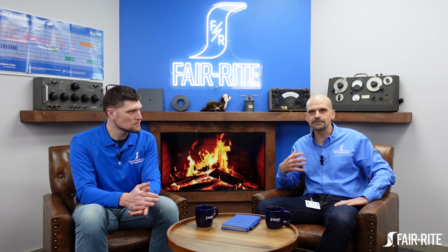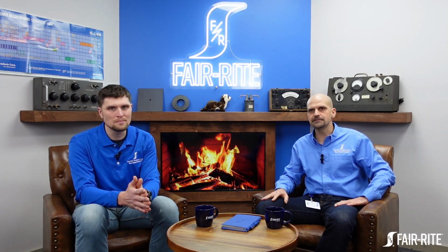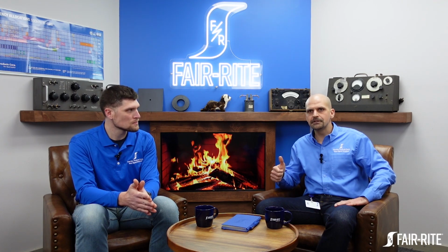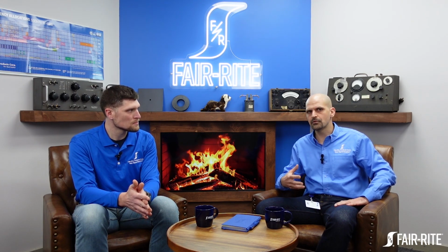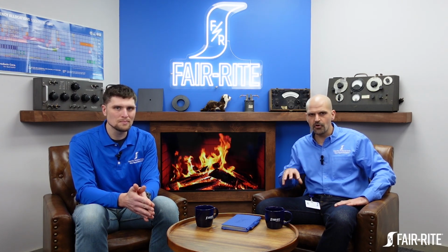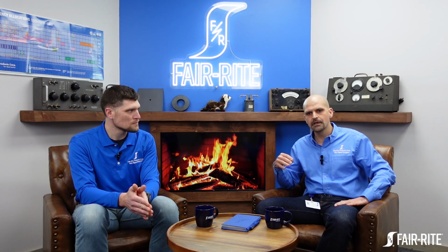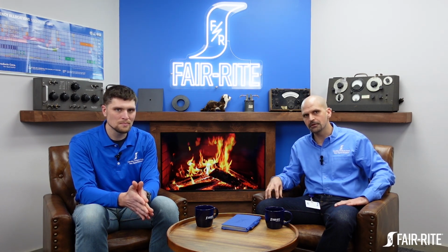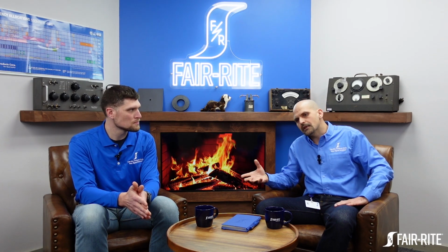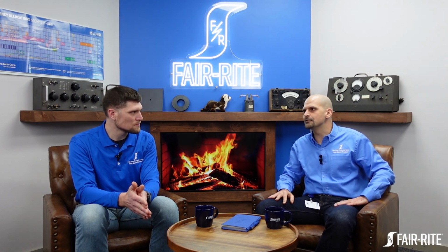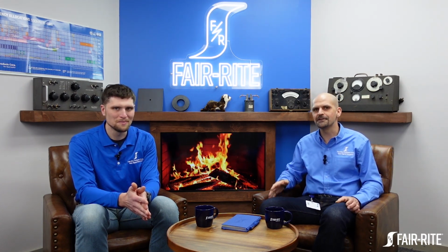And the second topic I always have to consider is the temperature, because ferrite itself is a temperature sensitive material. There is a very critical temperature for all ferrites, the so-called Curie temperature. Above that point, the material will lose its ferromagnetic properties. Thank God, when it cools down below that again, it comes back. So it's a reversible thing.